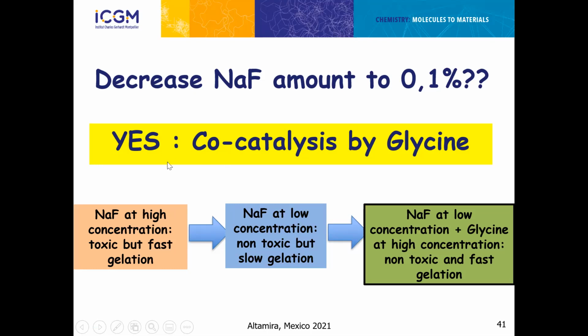The idea is to add something to activate, because at 0.1% of sodium fluoride, you can see clearly here, 0.1% concentration, it's not toxic, but the gelation time is very slow. As I mentioned before, at 0.3%, it's fast gelation, but it's toxic. And what we found is that if you mix F- and glycine, an amino acid, it's possible to manage your gelation time, and the cytotoxicity is very, very low.